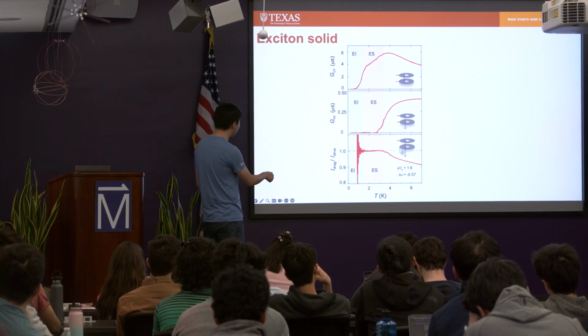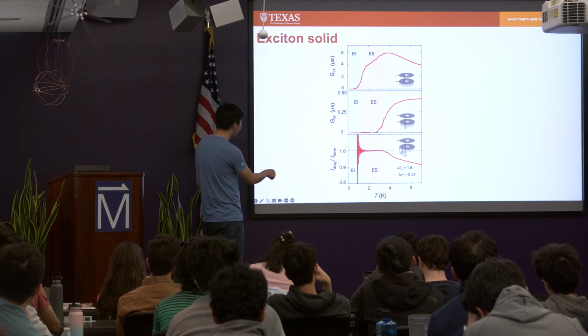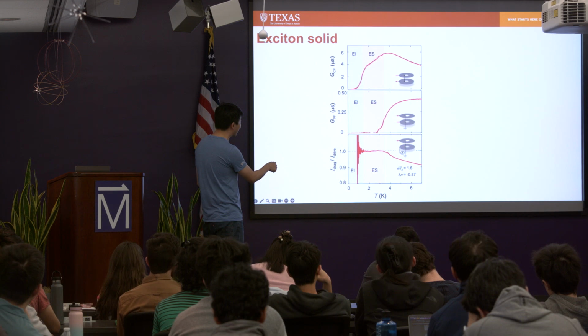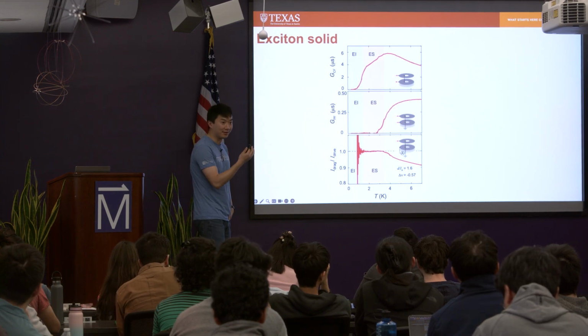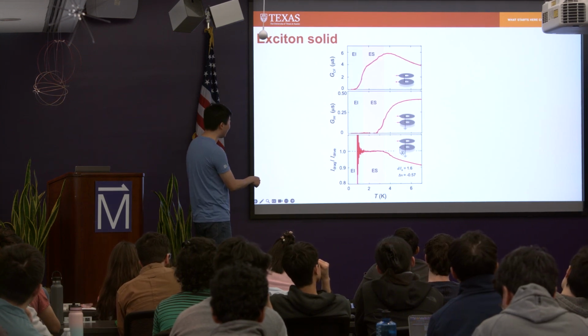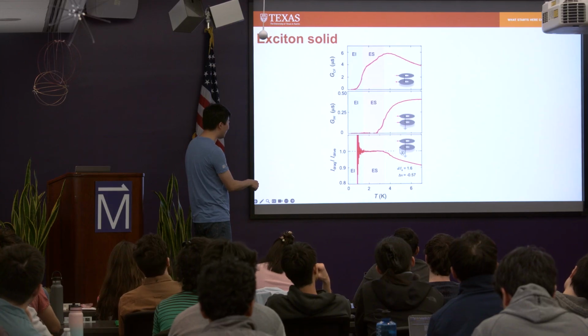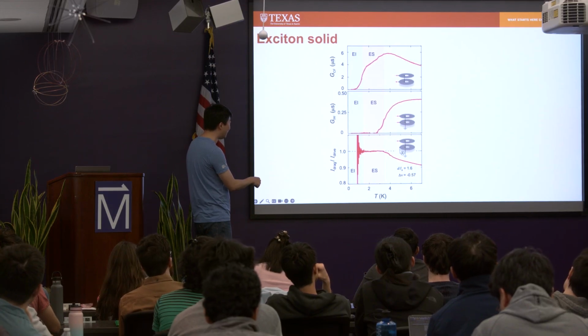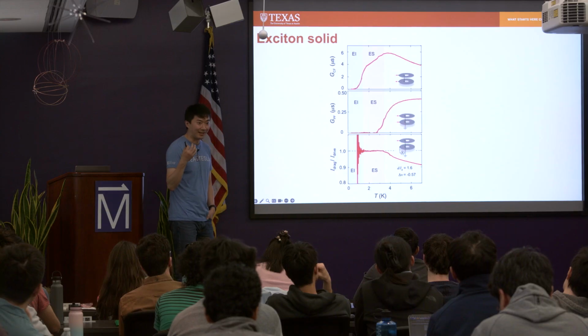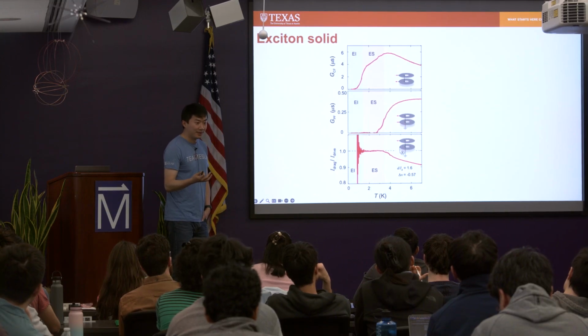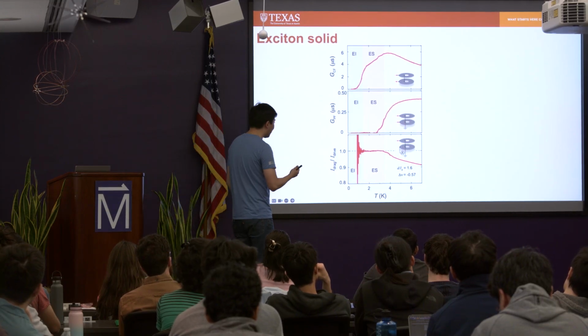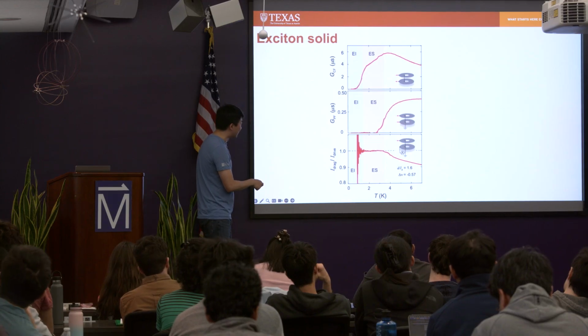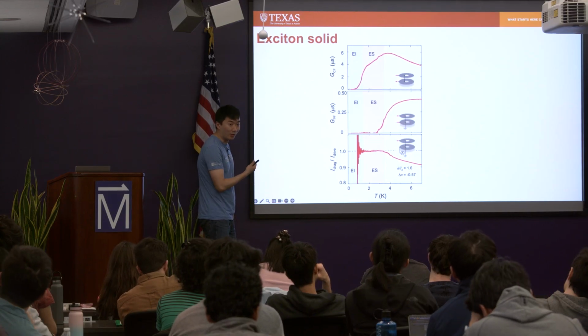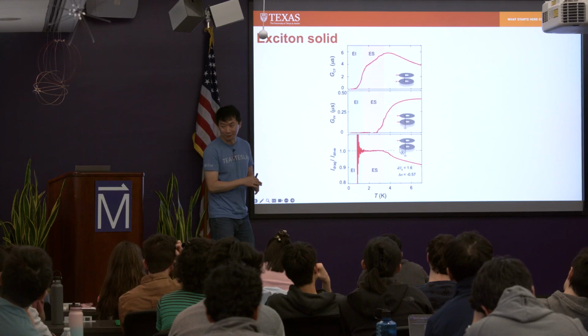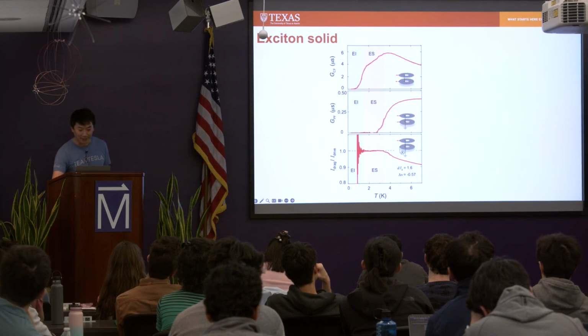And what makes the insulator very intriguing is how it warms up. When it crosses a threshold of about 1 Kelvin, right? Parallel flow is still insulating. Counterflow starts to develop non-zero resistance or non-zero conductance, right? And then if you do drag measurement, you realize that this, whatever insulator it is at low temperature, warms up into a state that looks like a superfluid, right? It exhibits all the superfluid signatures. The issue is that this is a 2-terminal measurement, so we don't really know whether it's a normal fluid or a superfluid. So we go to a Hall bar sample to double check,